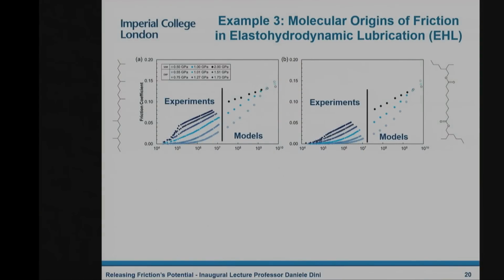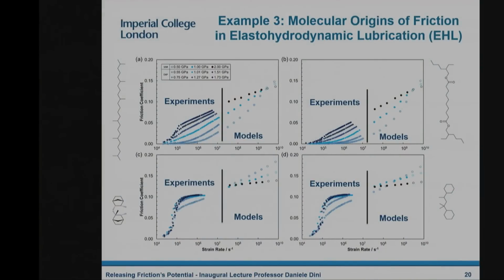And we managed to, in a way, push the models to scales that we had never pushed these models to before, and see that actually what we see in the experiments, which for very long chain molecules is that you get a low friction that rises with the increased shear rate, can be mimicked by the models that we developed. And this can be done for all molecules, but also you can capture the subtle differences between the different kinds of molecules, because if you don't have long chain molecules, and instead have something more bulky, you can see that there is again a match, at least in trends, between the experiments and the models.